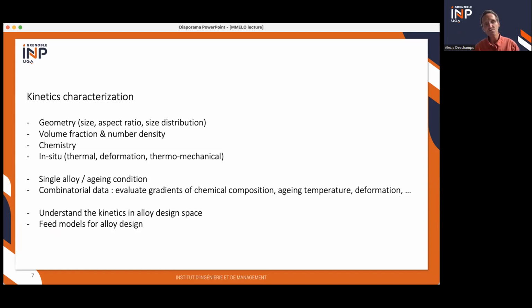So what we've been trying to develop is a way to do that in a kind of combinatorial way, to do that not on single arrays, but on gradients of chemical compositions. And gradients could be of composition, but could be on the other parameters as well. And so when you get this data in situ and maybe on combinatorial data, if you're lucky, then you can try to understand the alloy kinetics in alloy design space. So alloy design space is a space of chemical compositions that you can play with, or temperatures, deformation, and so on. And of course, you can use this data to feed models that then can be used for alloy design.